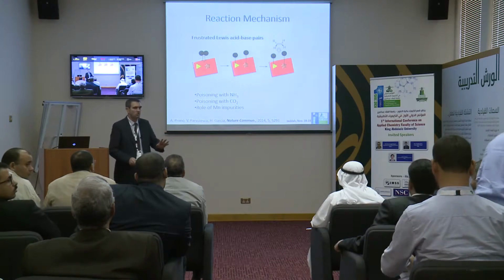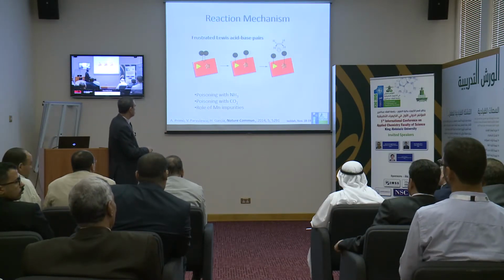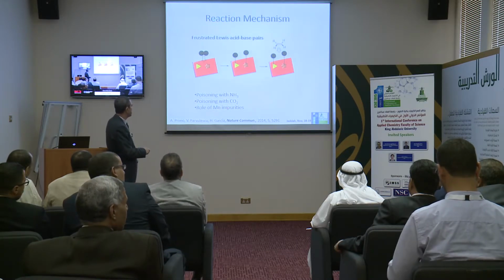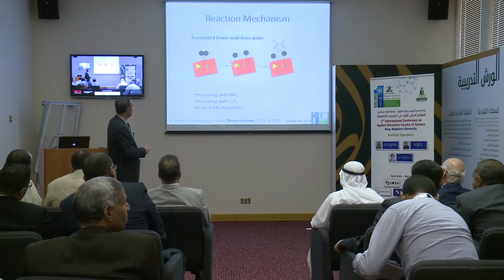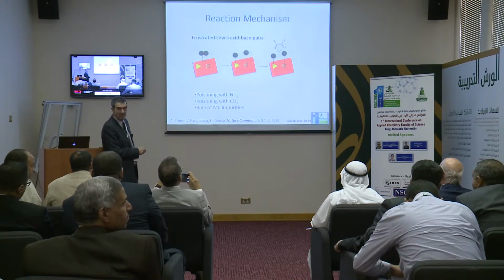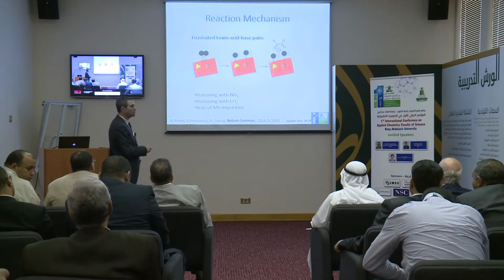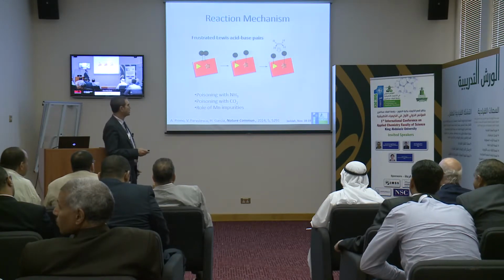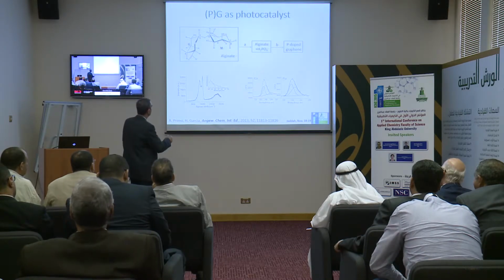So I have 2 more minutes. So also in this case, we studied the influence of manganese, and it's clear that there is no influence. We make poisoning with base to show that we need acids. We make poisoning with acids to show that we need a base, and the reaction mechanism has been proved.